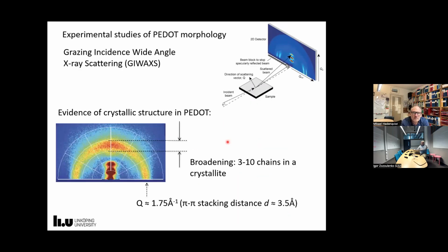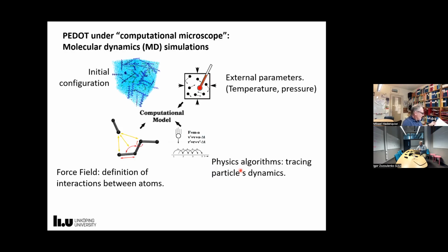Okay, and this is a typical picture of GIWAXS of PEDOT. And basically these peaks correspond to the periodicity. When you calculate this periodicity and relate it to real distance, you will see that this corresponds to the pi stacking of crystallites in the PEDOT. And the broadening of these peaks tells you how many chains you have in crystallites. And typically this broadening corresponds to 3-10 chains in one crystallite.